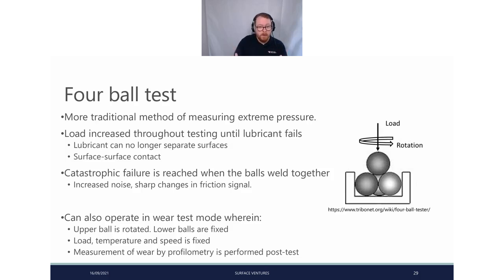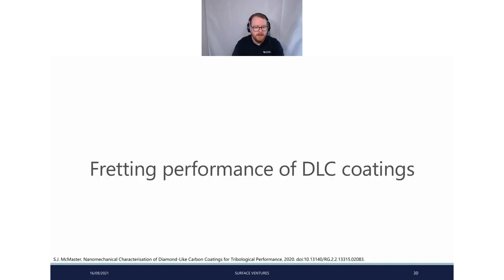And with a well-built fretting machine, you can instrument way more things and measure way more things than you can in a 4-ball test, just because the geometry is much more difficult to actually measure this. We can tell with a load, and then our catastrophic failure condition is essentially when we have sharp changes in the friction signal, whereas with a good piece of fretting equipment, we can keep the test going. We can say, okay, the friction's increased, what's happening in the contact, and so on. And of course, this can also operate in a wear test mode. So we just keep the load fixed. Lower balls are fixed, the upper ball is rotated, and we can measure the load, temperature. We measure friction between these, keep the load, temperature, and speed the same.